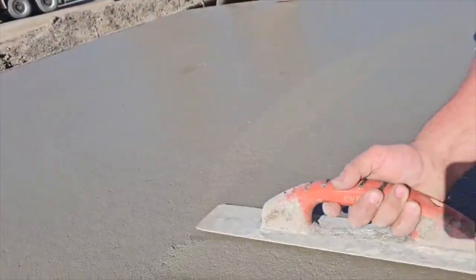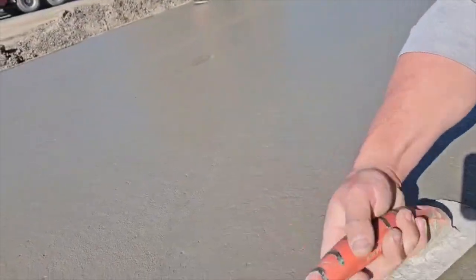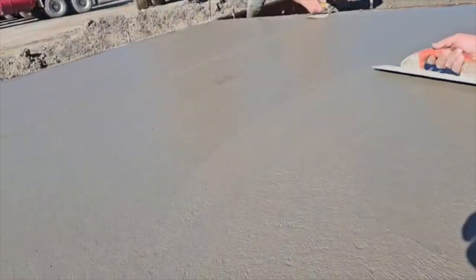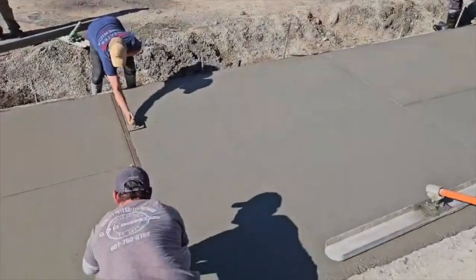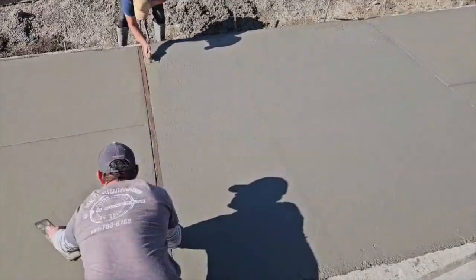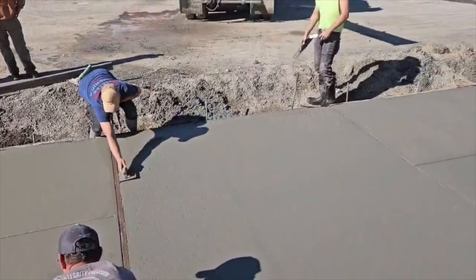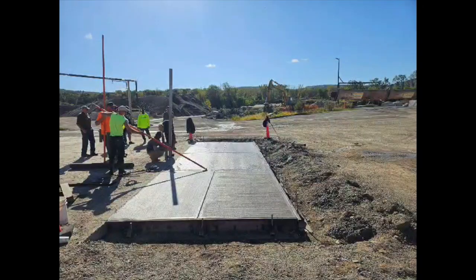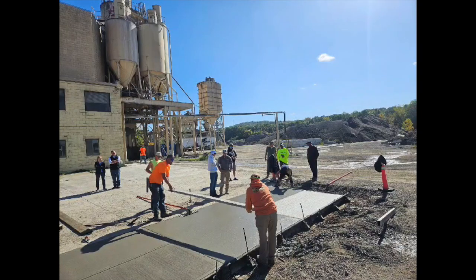When we did the 20% glass on the second test, the slump was about a 4.5, the air was about a 5.5. So it was a little bit looser, but was still pretty sticky starting out. I should mention that we did use 2% accelerator in this, and the sun came out, so that can contribute some of the stickiness. But also the little bit higher slump helped as well. There was plenty of cream. The surface closed up easily and broomed very nicely.